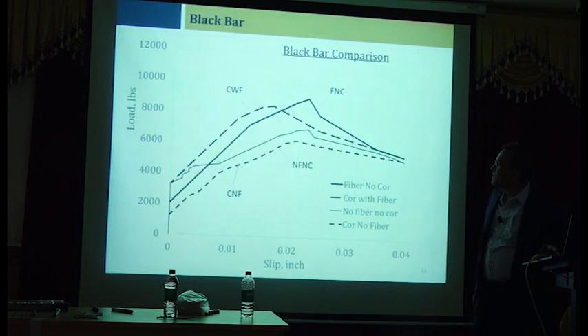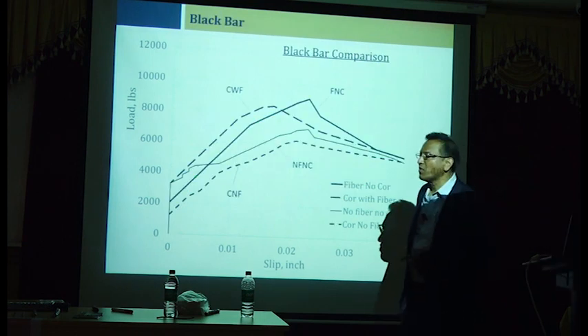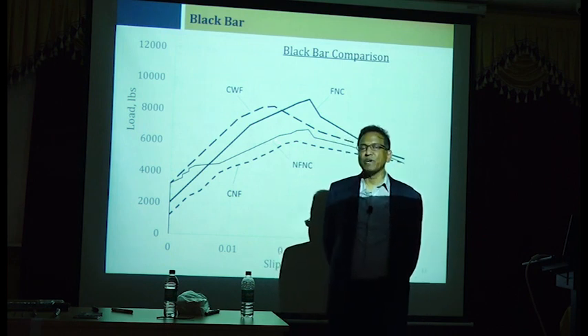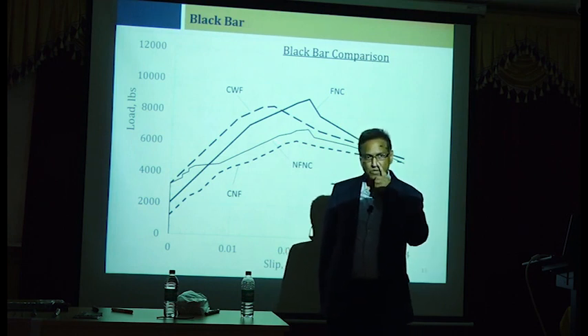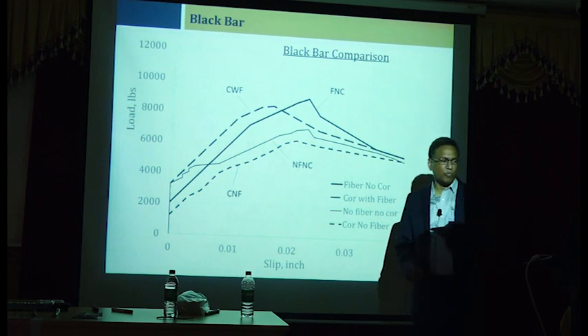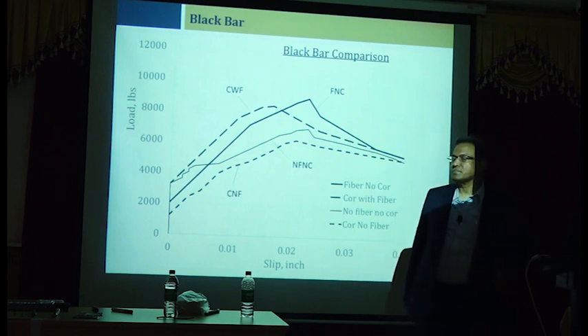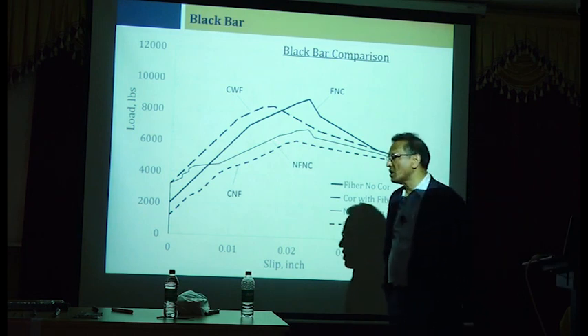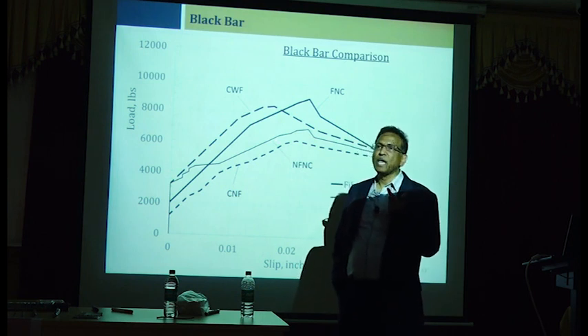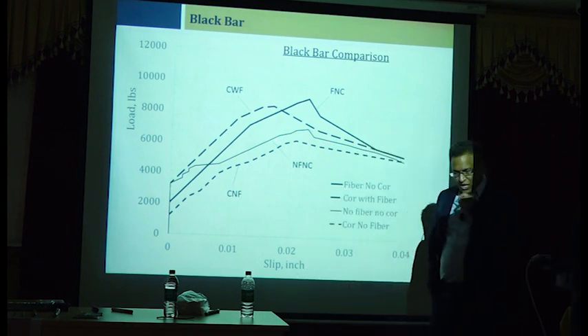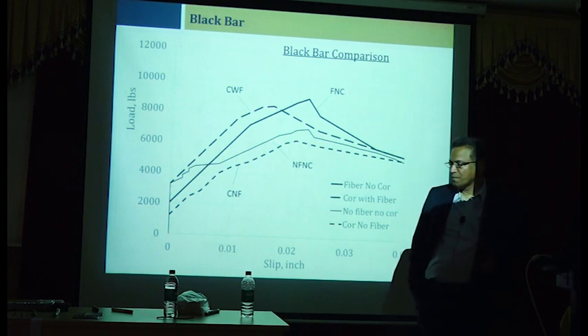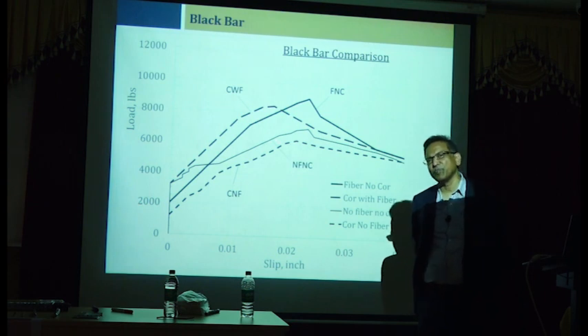And then one of the things we did was we used fiber in our concrete to reduce the crack widths and to improve the corrosion performance. And on both counts, we were very successful. So the addition of normal polypropylene fiber, of course, I decided on very high volume or high fiber dosage, like 10 pounds per cubic yard. I don't know how much it will work out to be in terms of kilogram per meter cube. Probably it's about 4 kilograms per meter cube or something like that.